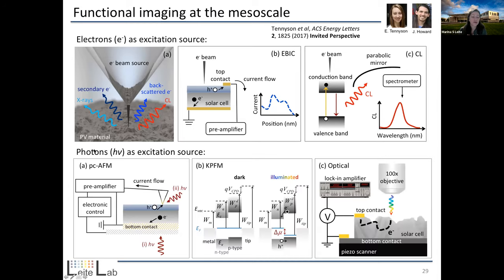However, if we use photons as our excitation source, we can do a one-to-one comparison as long as we calibrate the system properly and we take into consideration the difference in the scale that we're dealing with, both at the nanoscale regime and at the macroscopic regime, where I showed you that light IV curve. So in essence, the light IV curve that I showed to you is super informative, right? It tells us the average behavior of the solar cell, but it doesn't resolve spatially the contribution of each one of those mesoscale constructs.